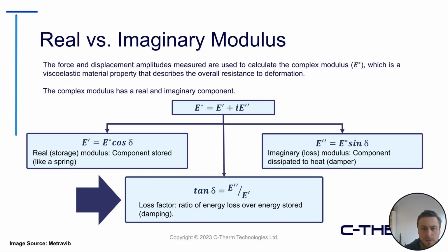If we take the force and displacement amplitudes measured during a DMA experiment, we can use those to calculate the complex modulus, E star, which is the viscoelastic material property that describes the overall resistance to deformation. This complex modulus has a real component and an imaginary component, which can be separated using the measured loss angle delta. The real component, E prime, is related to the part of the material that stores energy and later releases it, like a spring. The imaginary component, or loss modulus, is the part that's dissipated into heat, like a damper—this is what we're more concerned with for damping applications. The tangent delta relates these two moduli, as it is the ratio of energy loss over energy stored, so we can see its clear relationship to damping.